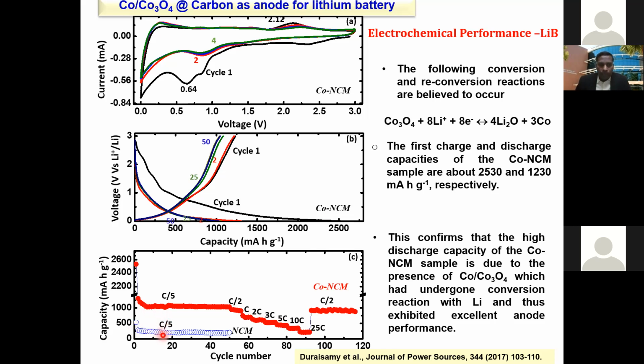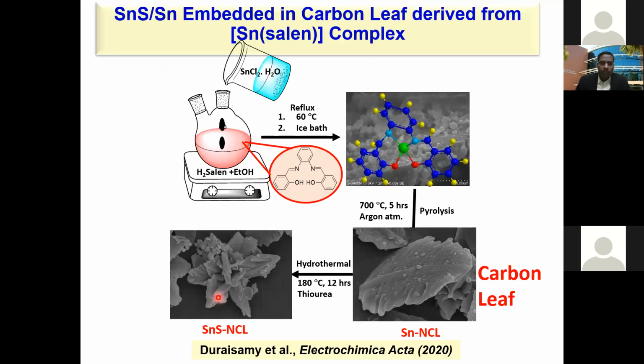Whereas the pristine carbon generated using the ligand shows very limited, very low capacity. So it means the material consisting of carbon, cobalt and cobalt oxide can be a potential anode material where we could get 1000 mAh as a capacity. Then I move on to tin sulfide.